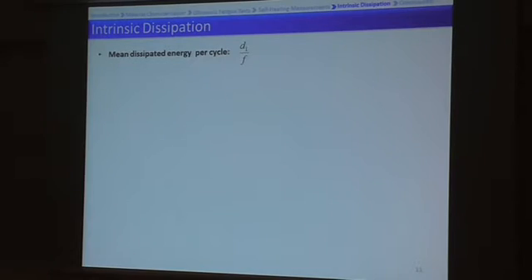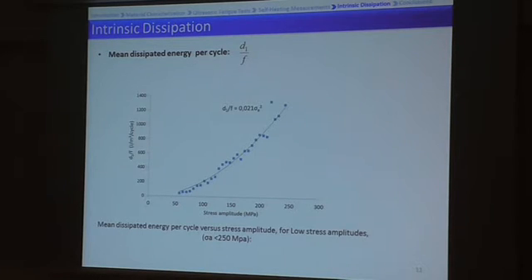Afterwards, by dividing this dissipated energy by F, which is the number of cycles, we can obtain the variations of mean dissipated energy per cycle versus stress amplitude for our material under ultrasonic fatigue loading. And the important result is that in our case, the dissipated energy per cycle is a quadratic function of the stress amplitude.